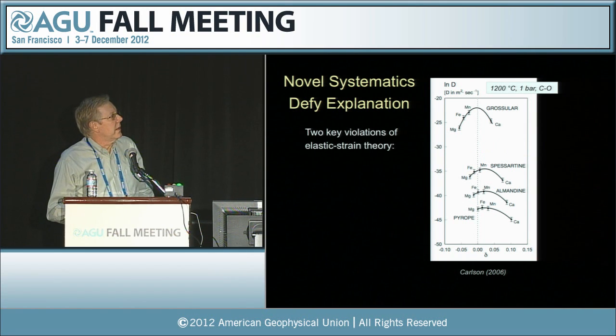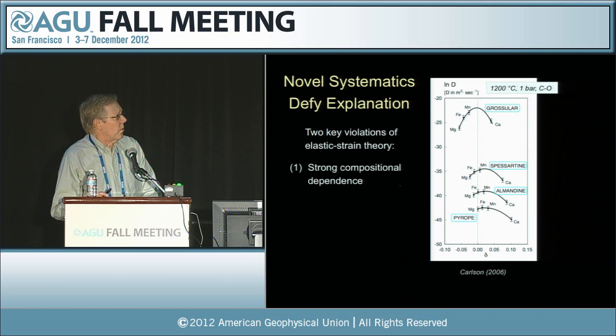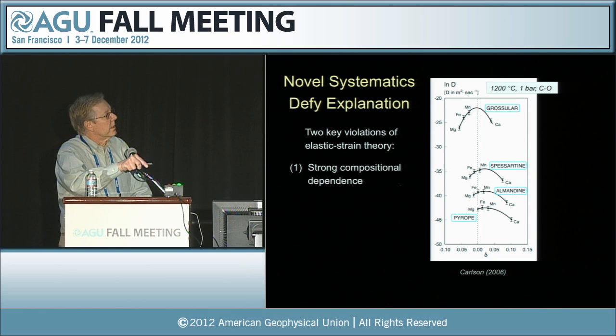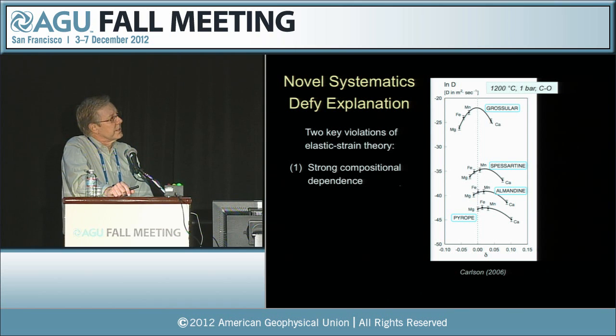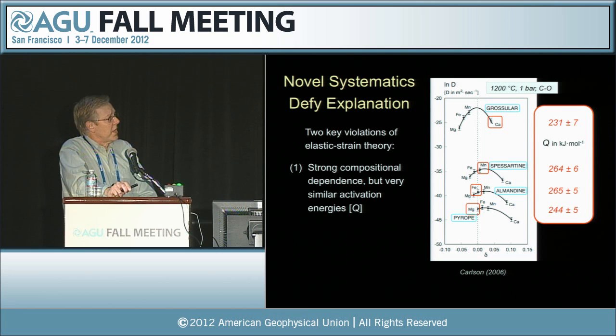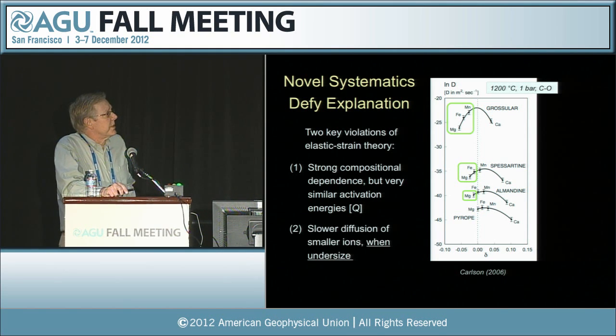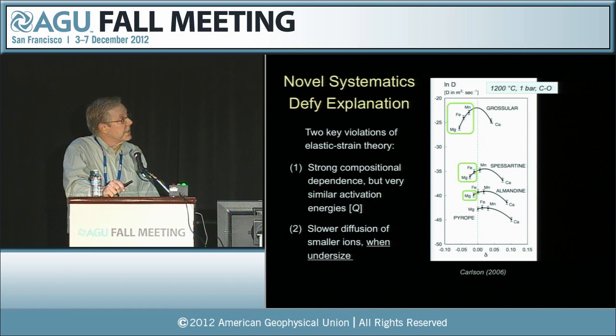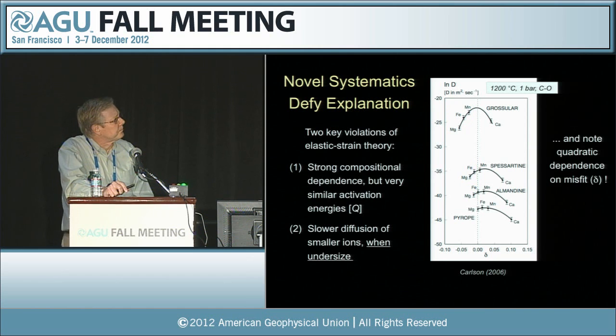This illustrates two key violations of our existing theory. One is this very strong compositional dependence here, which should be paired, under existing theories, with an equally large variation in the activation energies. But in fact, measured activation energies for self-diffusion are very close to one another. They're all within about plus or minus 6% of their central value. Another problem is that we see in these data slower diffusion of smaller ions when those ions are undersized. And of course, existing strain theory would tell us that smaller ions should always diffuse more rapidly.